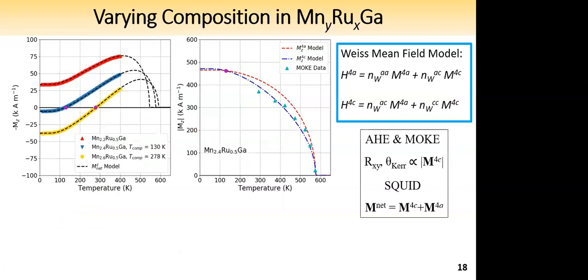So now looking at the mean field data, the magnetization curves at 0 applied field were fitted using the Weiss mean field theory model, described by a system of linear equations, which is shown in the blue box, and the curves are shown here on the left-hand side. In the middle, I show the calculated 4A and 4C magnetizations, and the triangles represent temperature-dependent MOKE data that was collected from the MOKE microscope. And as I mentioned before, the Kerr effect is proportional to the manganese 4C. And so we can see we have a good agreement between the model and the data, which validates our calculations.